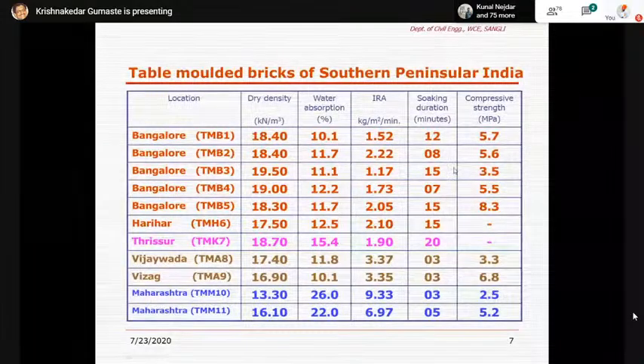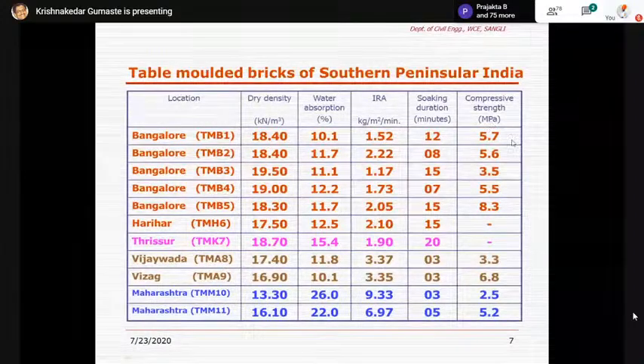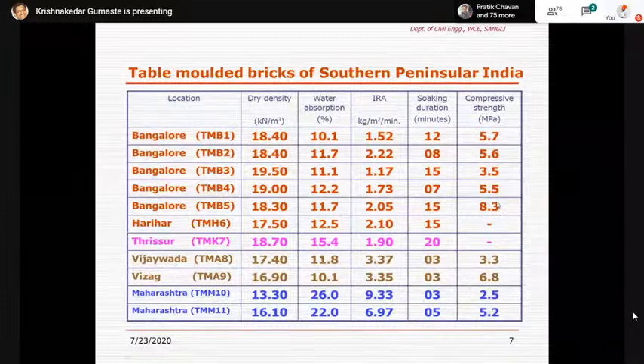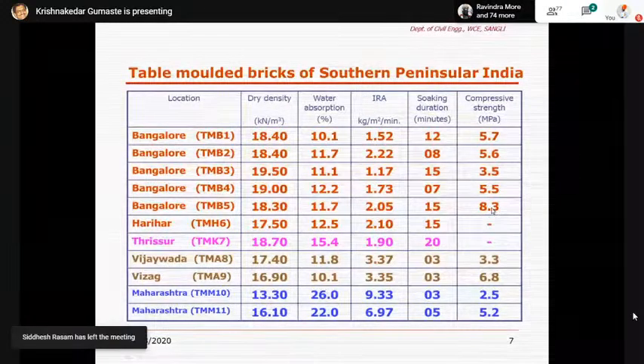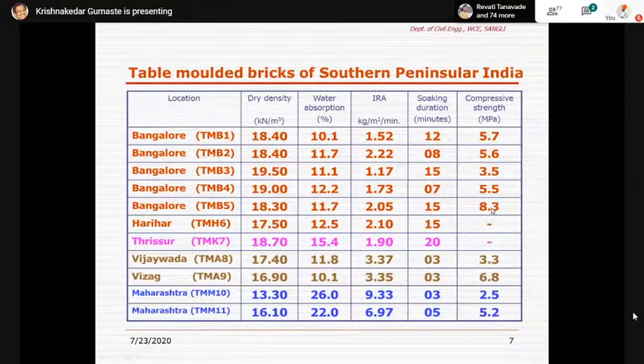See the compressive strength. When I say compressive strength of brick, it is as per the codal provisions: you dip the brick in water for a minimum of 24 hours and then test it in wet condition for the strength you can get from any building unit. The wet compressive strength of bricks of the southern peninsular region comes to about 8.3 megapascals, and the range of 2.5 to 8.5 megapascals is the kind of strength available in the southern peninsular states. When you compare with Western countries, bricks of the US or other Western countries start with 10 megapascals as the minimum value. So we are in a lower zone. The highest strength of ours is the lowest strength of the Western building units generally observed.